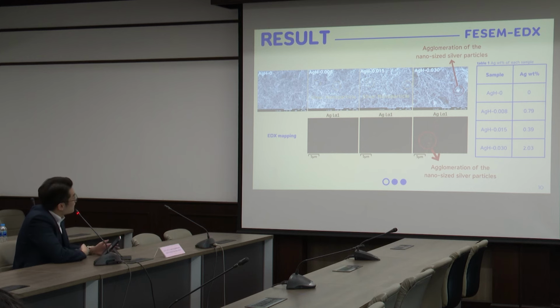We confirmed this again by the EDX mapping, which shows that in the 0 phr sample, silver nanoparticles are not present in this structure, and as the concentration is increased, the mapping presents the silver nanoparticles like orange dots in these three pictures. And again, this picture of AGH 0.030 phr shows the accumulation of the silver nanoparticles, as agreed with the FESEM image.